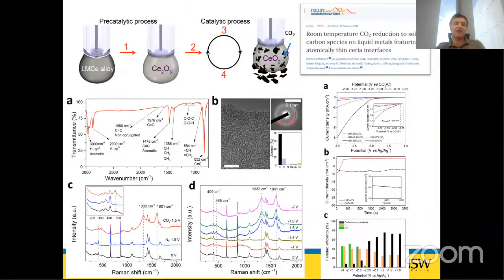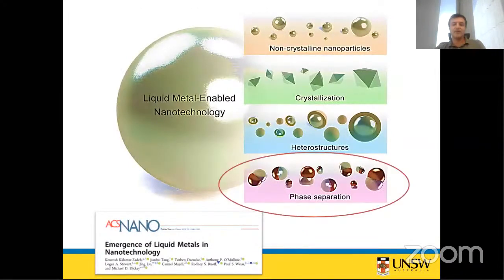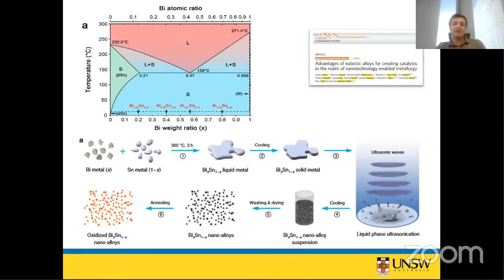The world that the electrode does not need to be solid. The electrode for conversion of CO2 can be liquid, and it opens up, as I said, the world that we can have the byproduct as a solid byproduct of this conversion. It doesn't need to be a gaseous or liquid byproduct. Phase separation, here we are going as an interesting example to look inside liquid metal.